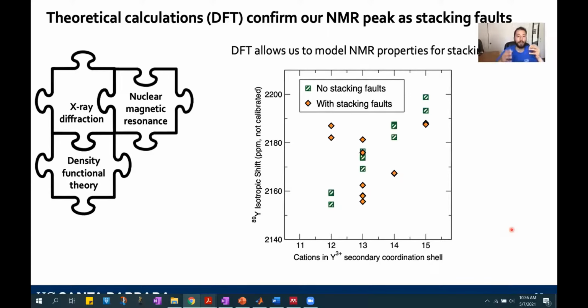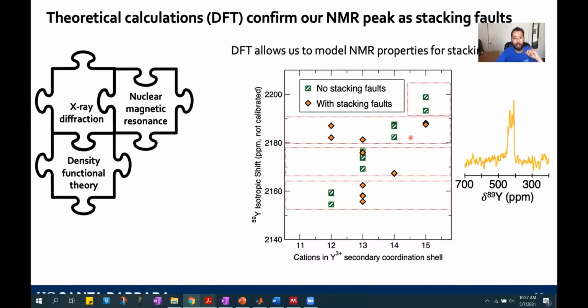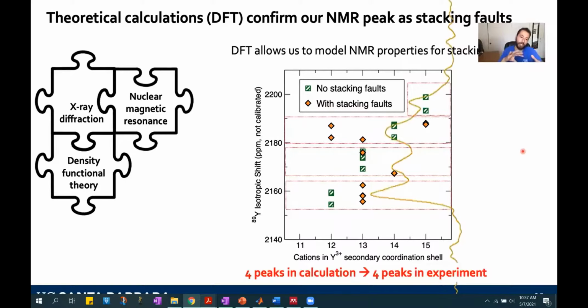And we use DFT to model the NMR properties of structures with stacking faults. When I look at this plot, in green, I have structures that give me no stacking faults. And I can see that my peaks are really well reproduced here. I see 4 bins that, when I look at my NMR spectrum, correlate to these 4 peaks. And that's when I have no stacking faults. I can even emphasize this when I turn that plot to the left, and I can see that it really falls well within these little bins.